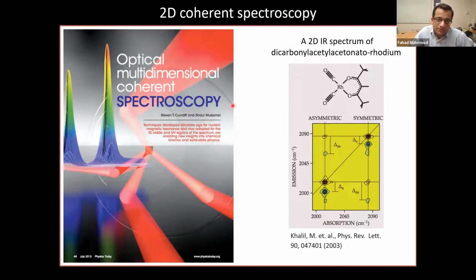When I do a 2D optical spectroscopy, I have two light pulses going in. And so what you end up getting are these 2D maps where you're plotting either absorption or some property of the system, such as its conductivity or susceptibility, as a function of two different frequencies. And this is a very useful technique because now I can not only look at the linear spectra, but I can start looking at cross terms between different mode couplings. Okay, so this was a well-established tool in the infrared range, and it's been very useful for molecular systems or liquids, because those excitations, let's say, vibrational modes, are usually in the infrared range.